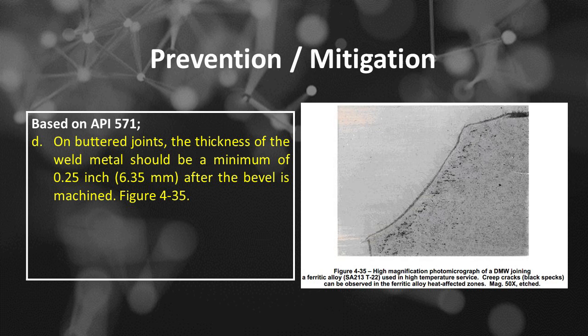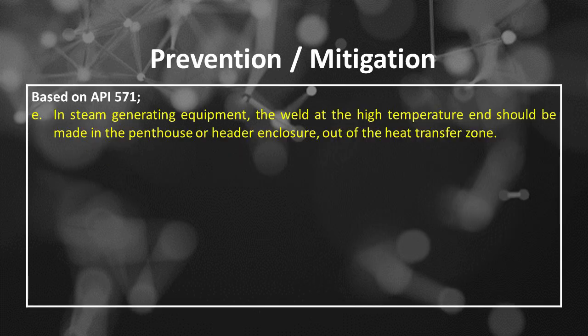Figure 4.35, high magnification photomicrograph of a DMW joining a ferritic alloy, SA213T22, used in high temperature service. Creep cracks, black specks, can be observed in the ferritic alloy heat affected zones. Mag 50X, etched. The fifth is in steam generating equipment.